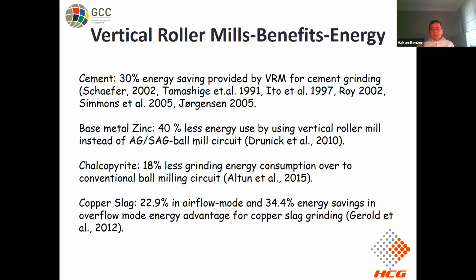Copper slag application is very predominant, and there are lots of copper slag grinding operations, especially in Asia. And in this case, the overflow mode of the vertical roller mills has been implemented. By saying overflow mode, the typical vertical roller mill design is air swept, so you transfer the material pneumatically. But it's well known that if we have the chance to transport the material mechanically, which is the overflow mode, we can have more energy advantages in the system.